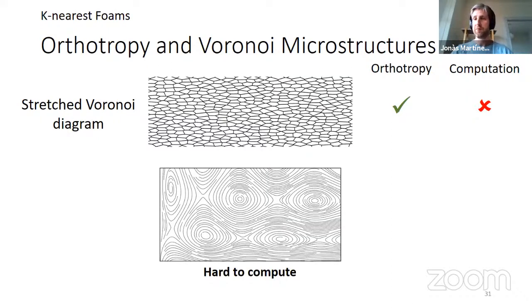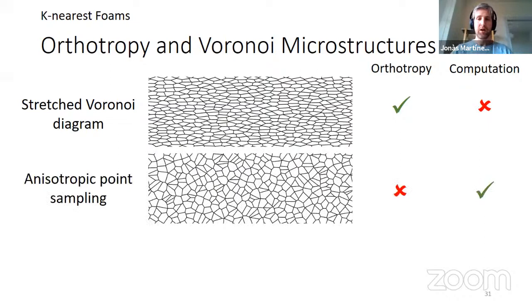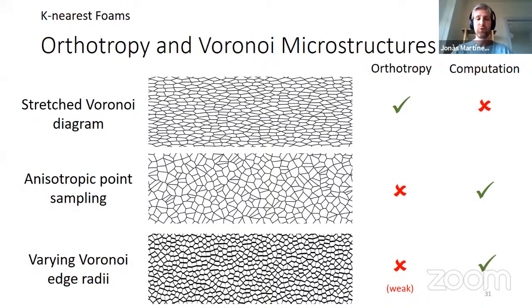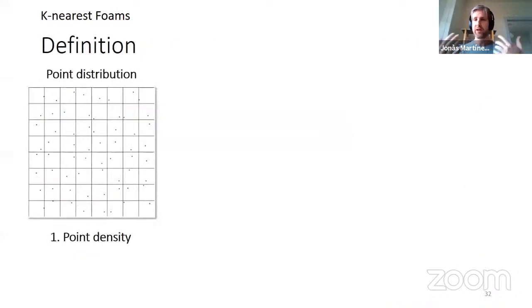But of course, this is quite difficult to compute when lifting to 3D, because either you do an inverse mapping or you compute anisotropic Voronoi diagrams, which are difficult to compute procedurally. Then we thought about doing anisotropic point sampling, but actually it doesn't induce any orthotropy. We even tried, for instance, to vary the Voronoi edges following some direction, but it didn't work. So we wanted to take another approach, and we thought about getting inspiration from laminate-like materials.